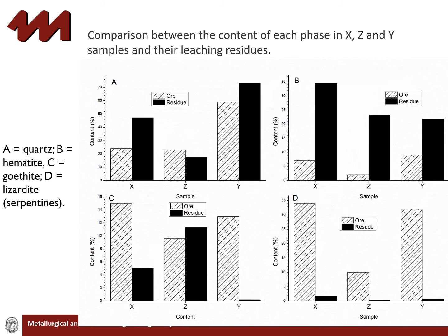The decrease from 34 to 1.5% of serpentines, mainly lizardite, in the X sample also indicates that almost all of the nickel was extracted from this phase, and goethite is the phase in the residue with more nickel. The higher amount of magnesium dissolution from serpentines affected the extraction of nickel incorporated into goethite. The amount of goethite in the X sample, unlike the Z sample, can be considered high and equal to 5%.